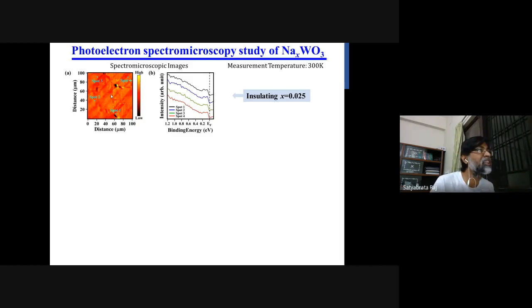So that's why you can see those steps as artifacts in the spectromicroscopy images. But surprisingly, if you measure any spot, the spectra is always insulating, and it shows 0 density of states at EF. That means the full images are actually insulating images.